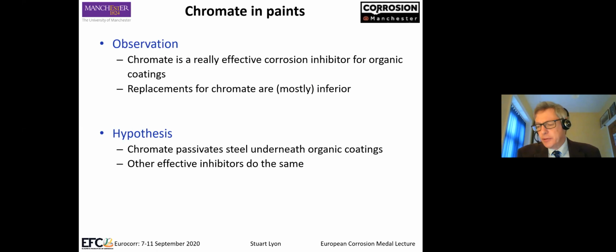So the first thing we looked at was chromate in paint, as many people have. Chromate is a really effective corrosion inhibitor for organic coatings, and replacements for chromate are mostly inferior. And one hypothesis was that chromate passivates steel underneath organic coatings, and other effective inhibitors therefore must do the same. It must be said, of course, that chromate at these low concentrations doesn't really passivate things.